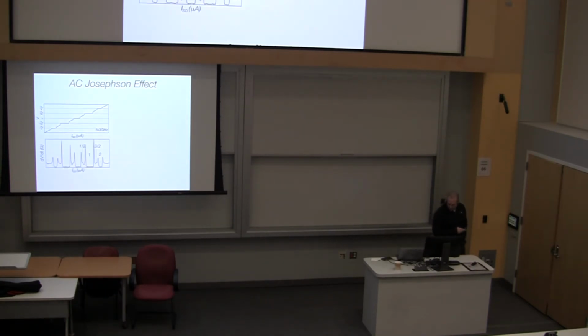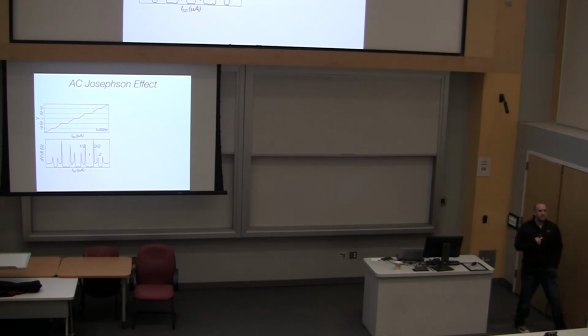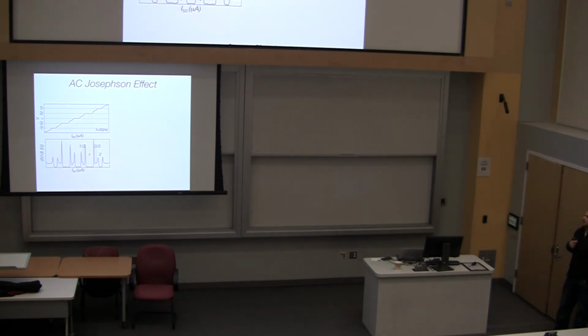So we did the AC Josephson effect for lead-doped tin telluride, by all intents and purposes the same as tin telluride, at least for this magnitude of lead doping. This is the measured Shapiro steps, where we see strong features at the integer plateaus. But in addition to these strong features at the integer plateaus, we start to see these half integer plateaus.